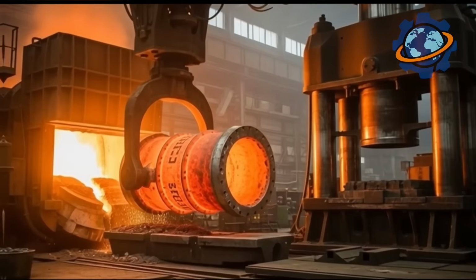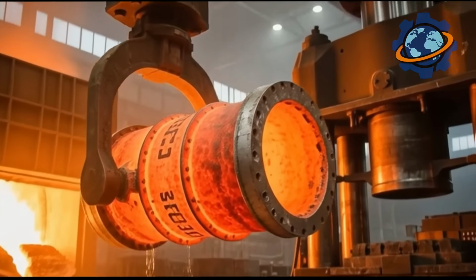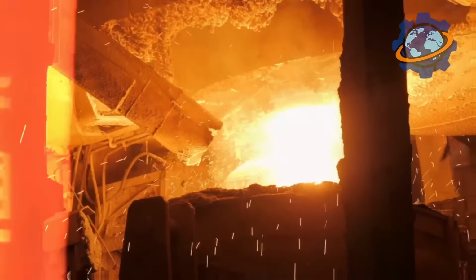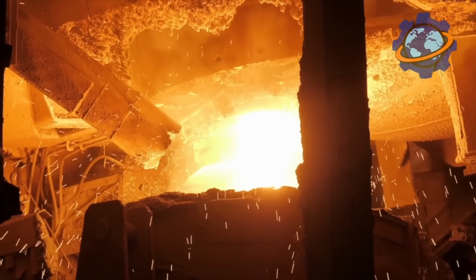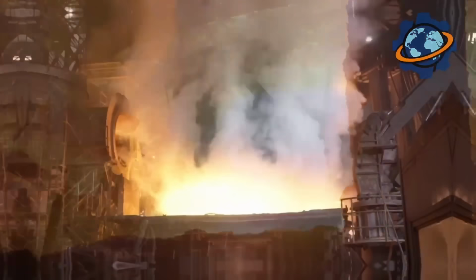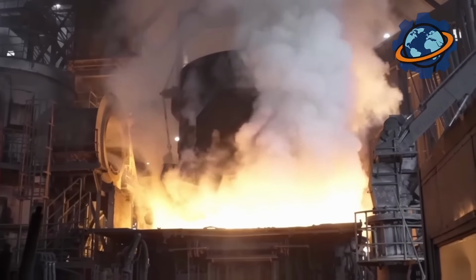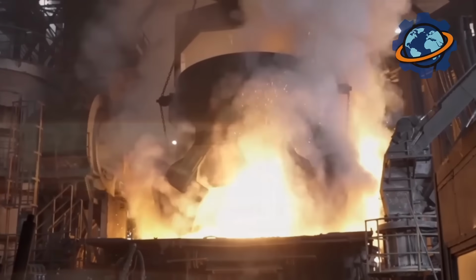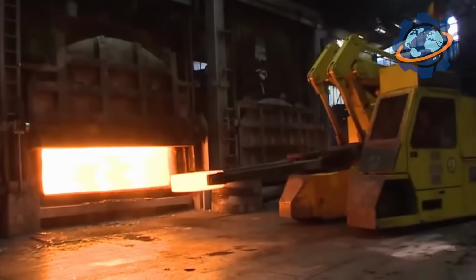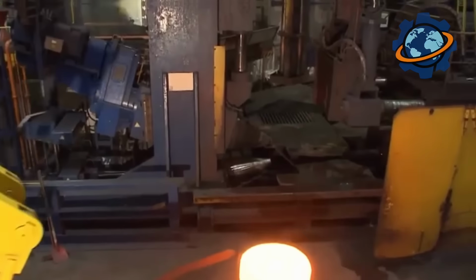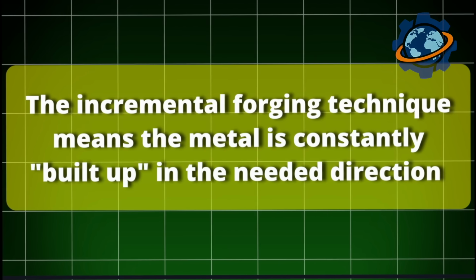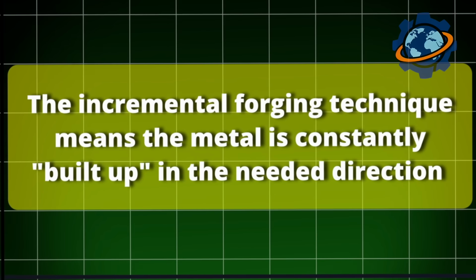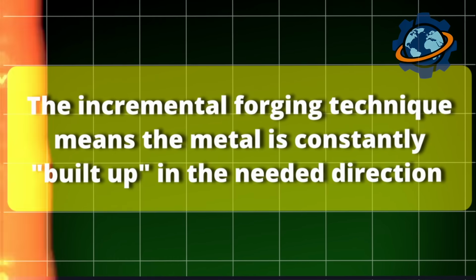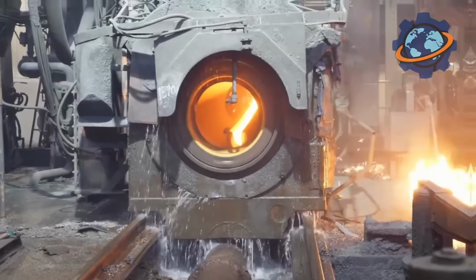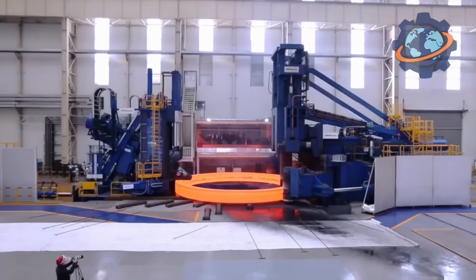The resulting ingot looks like a massive metal barrel. It's heated in furnaces where temperatures are many times higher than in a kitchen oven, then transferred to presses. The blank is first flattened, then pierced through, then rolled in a circle, each time rotating and hammering it so the structure becomes as uniform as possible. The incremental forging technique means the metal is constantly built up in the needed direction, while simultaneously being compacted, driving out voids and defects.